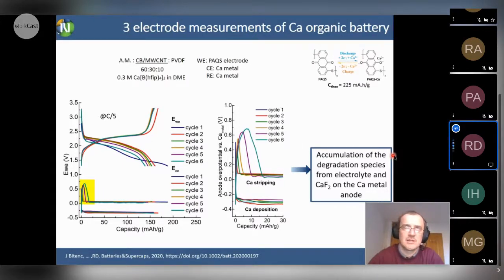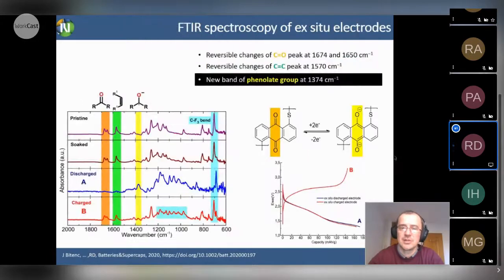Now there are 2 chances. Either we create some protection layer that will stop this continuous degradation of the electrolyte on the surface, or we need to develop new salts which will still enable room temperature reversible stripping and deposition, but without such severe passivation, or ideally without any passivation.